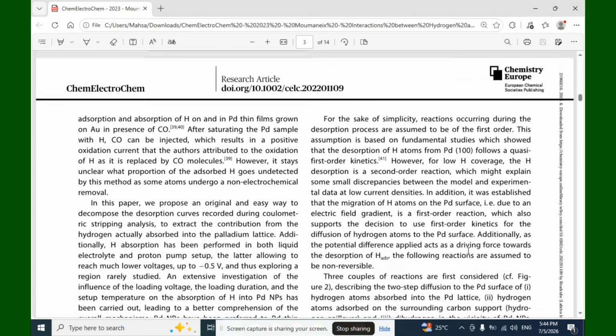For the sake of simplicity, reactions occurring during the desorption process are assumed to be of the first order. This assumption is based on fundamental studies which show that the desorption of hydrogen atoms from palladium 100 follows a quasi-first order kinetics. However, for a lower hydrogen coverage, the hydrogen desorption is a second order reaction, which might explain some small discrepancies between the model and experimental data at low current densities.